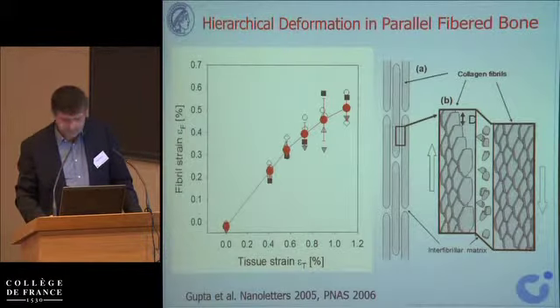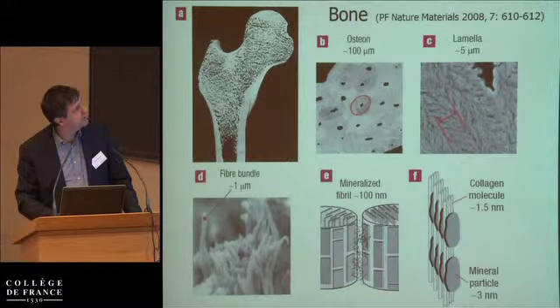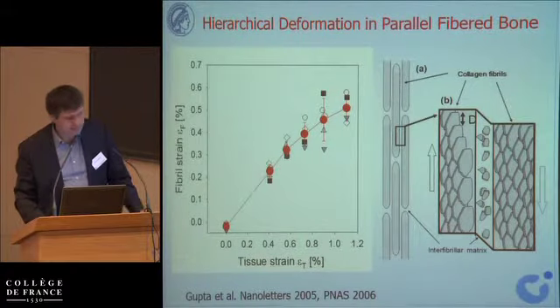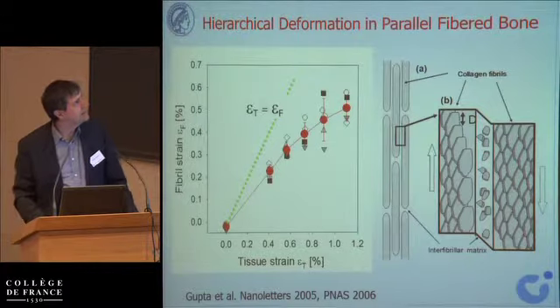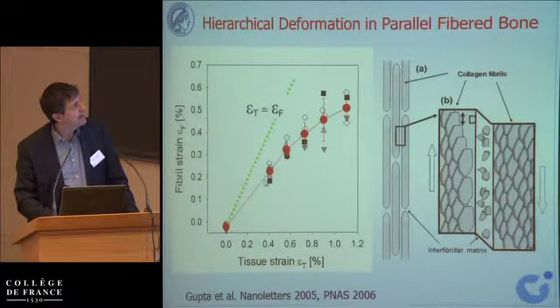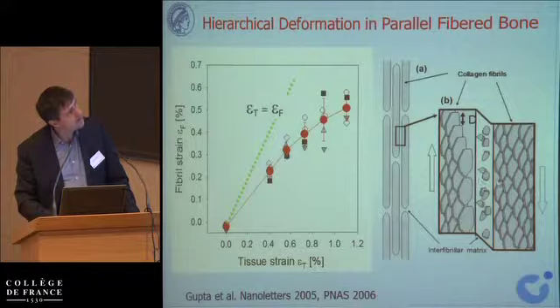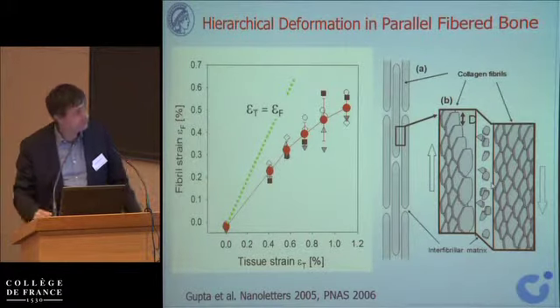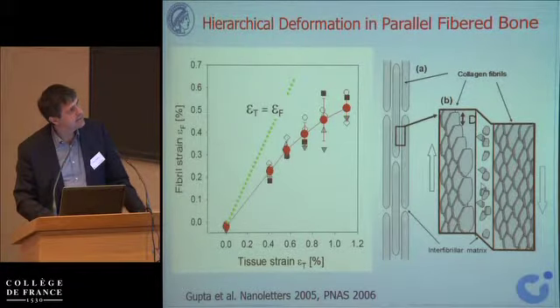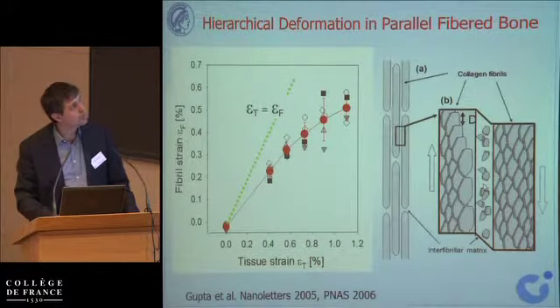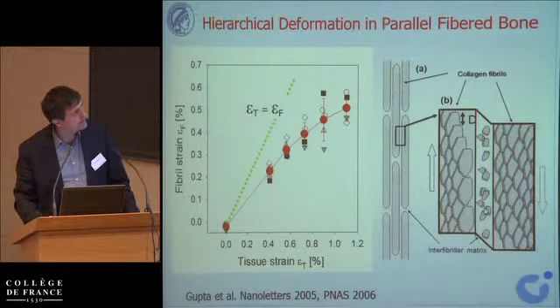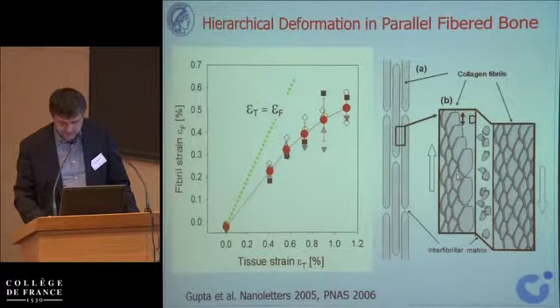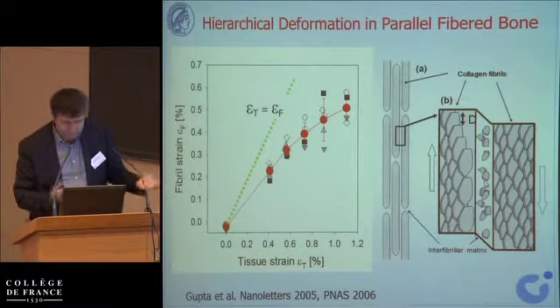So the same thing also exists in bone. So this is just an image of bone, which is also consisting of these collagen fibrils. The only difference to the tendon is that it's now reinforced with mineral particles. And doing the same study on bone, you find that the same is true, that actually bone is able to deform twice as much as the mineralized collagen fibrils. And the reason is that the interface between these blocks provide the deformation. In this case, this interface here is made of phosphorylated non-collagenous proteins and also some mineral in it and so on, but not as much as on the surface of the collagen. So here are two materials that do this.